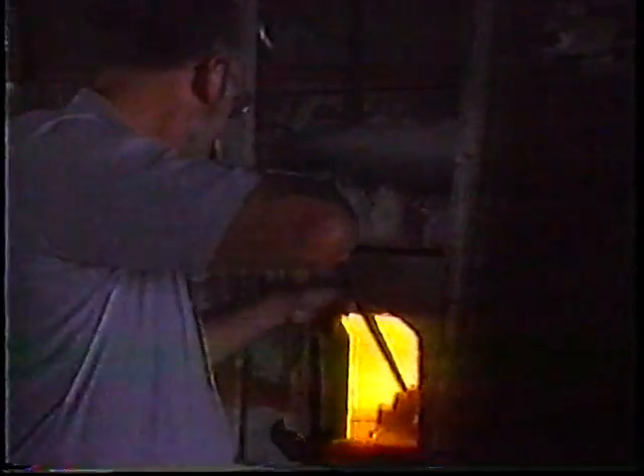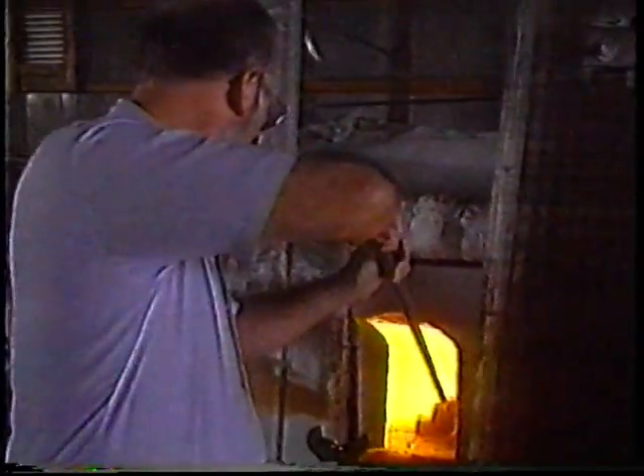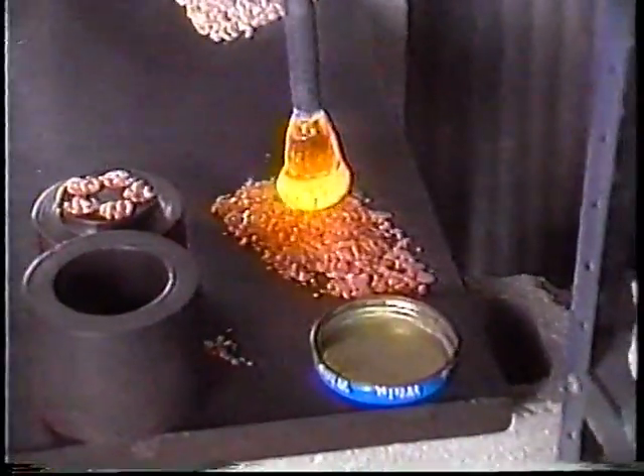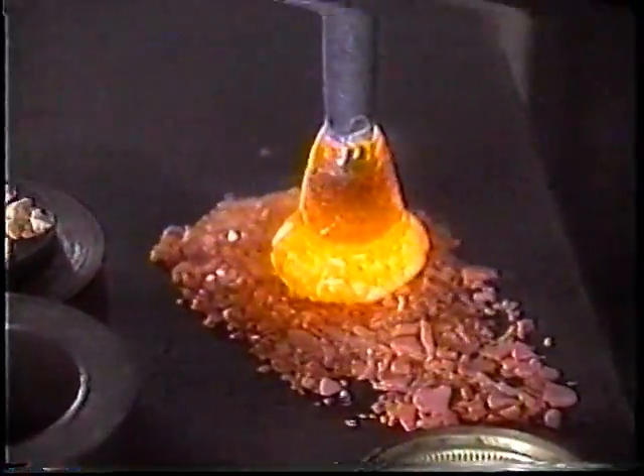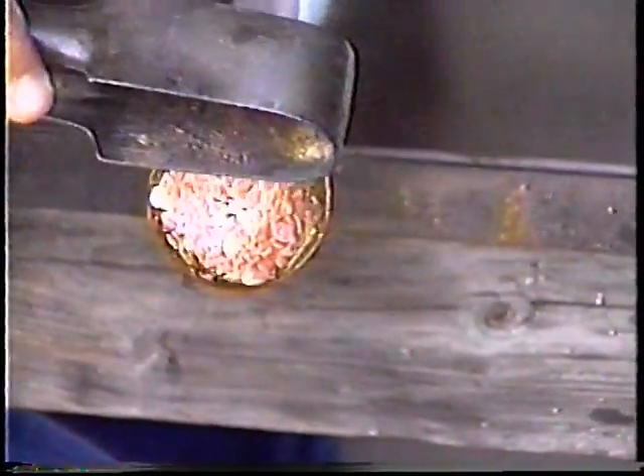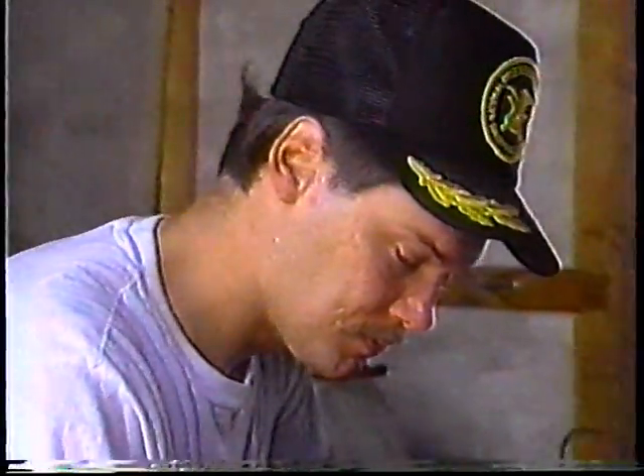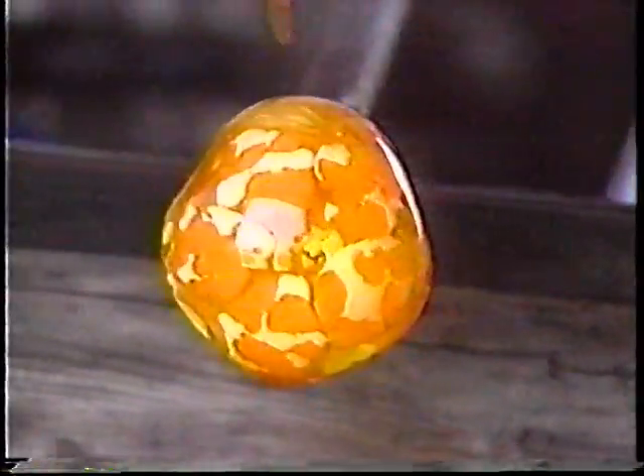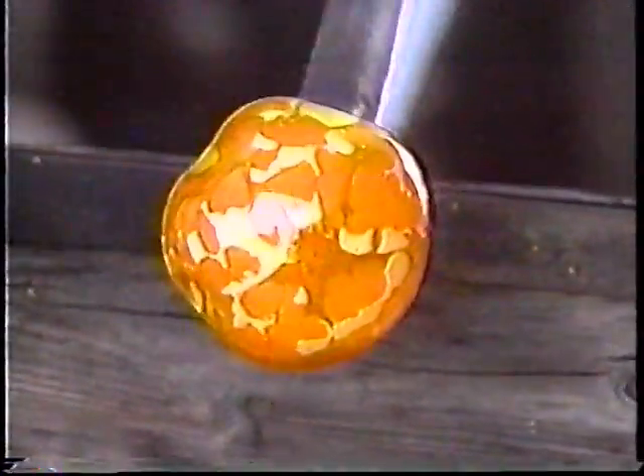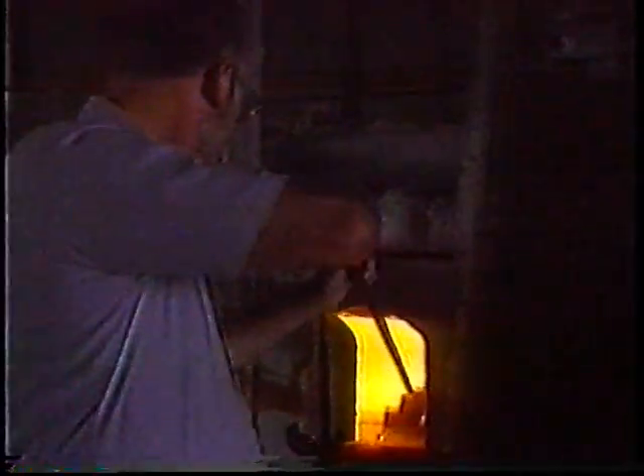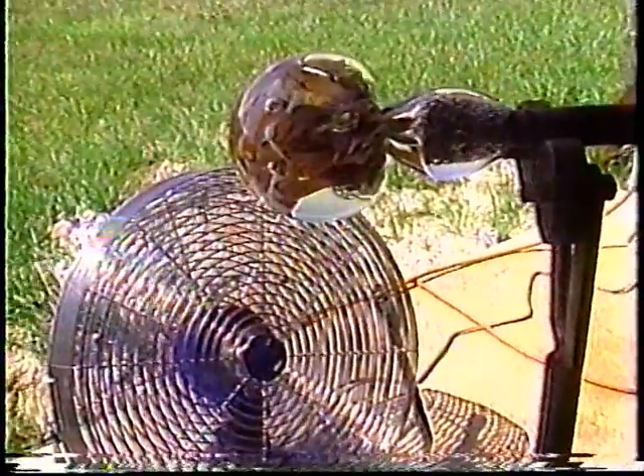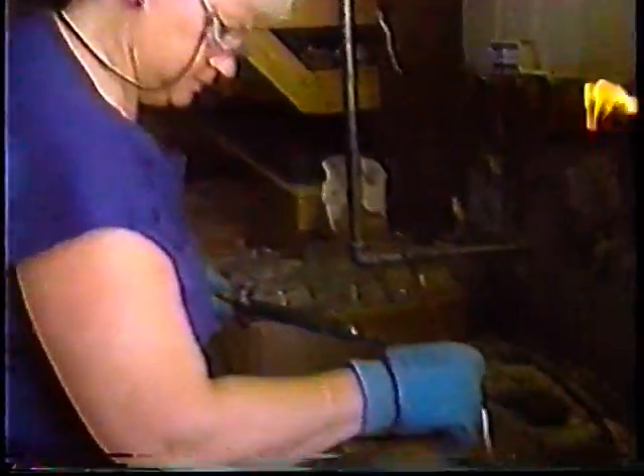Each week, 900 pounds of molten glass are heated at 2,800 degrees and turned into art with 5 layers of glass. While we were there, Monty and son Jim formed a paperweight. Pushes the soft molten glass down with the ice pick and makes a stem of the flowers. Then I take it and put a final layer of glass over top of it and put the finished shape on it. Then my wife takes it and lets it cool off to about 1,200 degrees, and then she takes a torch and stamps my name in the bottom of it.